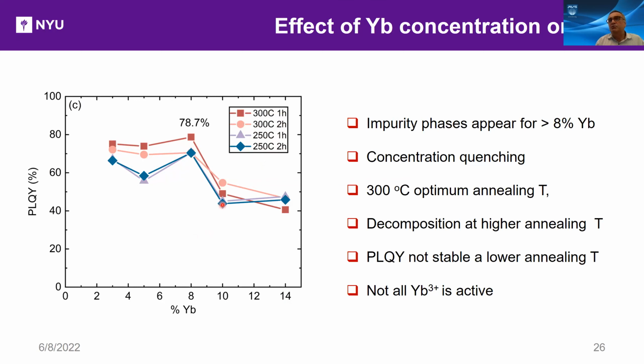It decreases above 8%, and this is consistent with impurity phases appearing when it's greater than 8% ytterbium. There's also a phenomenon that I don't have time talking about called concentration quenching. Basically, you can't have too many ytterbiums, and they exchange energy to lead the energy to a non-radiative defect, which then decreases the photoluminescence quantum yield. We've done different temperatures of annealing. 300 degrees centigrade is optimum annealing because it decomposes at higher annealing temperatures. And when we go below, photoluminescence quantum yield is not really stable.